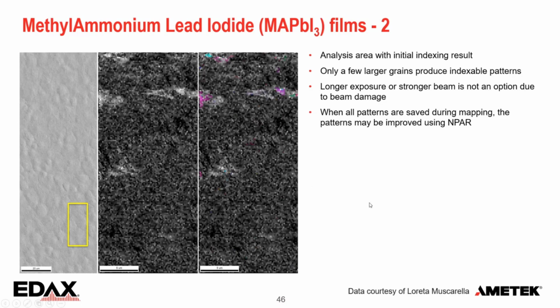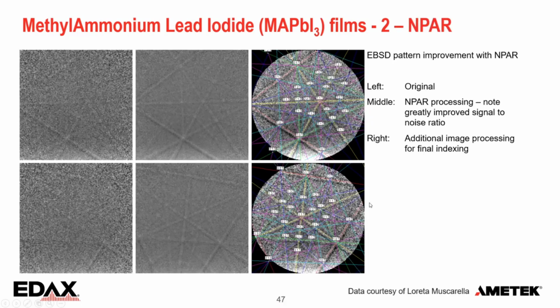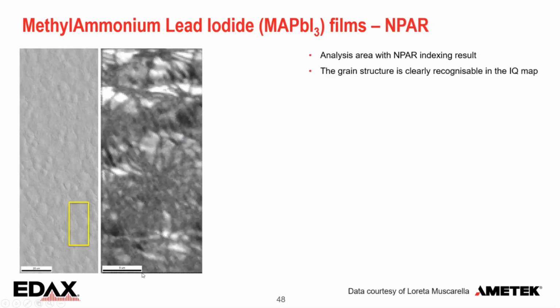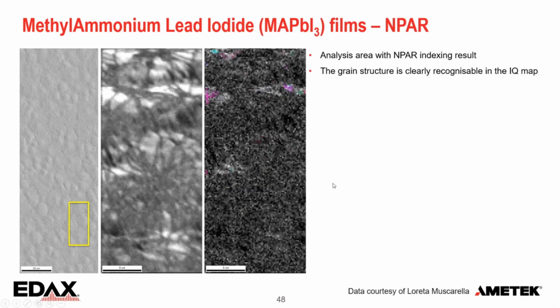But when we apply NPAR to that, then life gets a lot more interesting. So these are from the good patterns. With NPAR, it definitely gets a lot better. But even the poor ones improve so much that we can get this IQ map. And here we have a very clear grain structure. You can see the flowers almost again, so these radial textures that we also have here. But here they are different orientations.